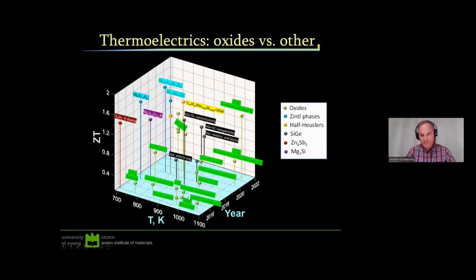During the last decade, quite significant progress was achieved for oxide materials, reaching values of 1.5, even for strontium titanate composite with graphite. But in most cases, the research results show gradual improvement due to various concepts, not as dramatic or drastic as in this case.